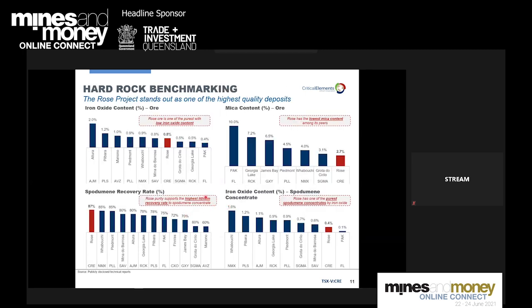Now, zooming in slightly, Rose ore is low in iron oxide and low in mica, two important impurities that are currently found in a lot of ores and concentrates going forward. So we're producing spodumene concentrate at a very high recovery rate, resulting in very low iron oxide content. And you can see our friends at Frontier Lithium, their PAC deposit, also has excellent low iron content.